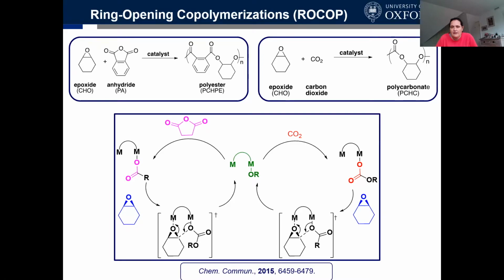It's long been my group's hypothesis that two metals are needed for this catalysis, particularly if the metals are light or first-row transition metals. You need two so that you can access that transition state and have enough low barrier to have rear side attack by the metal carbonate onto the epoxide. It's also worth saying that exactly the same mechanism works if instead of carbon dioxide, you have a cyclic anhydride. I'm not going to belabor the point, but on the left-hand side of this mechanistic sketch, you can also make polyesters by using anhydride epoxide alternating copolymerization.